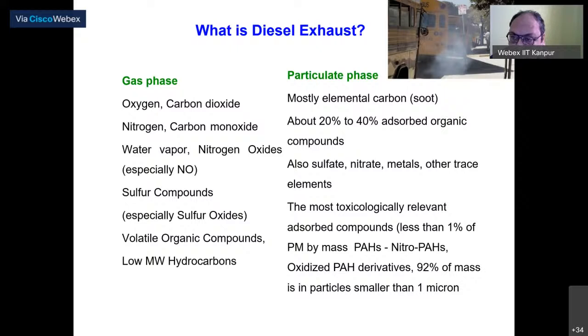Soot is again a mixture of several organic and inorganic compounds. There are several adsorbed organics on the particulate surface of the soot. There are traces of sulfate, nitrate, some refractory materials, and other trace materials. And then in terms of organics, we have something called SOF, soluble organic fraction, out of which polyaromatic hydrocarbons, especially the nitro and oxidized derivatives, are the compounds which are most toxic and are of interest as far as their measurement, their removal or their mitigation is concerned, from the various health and other benefits which are involved. I'll talk about that in a later slide.